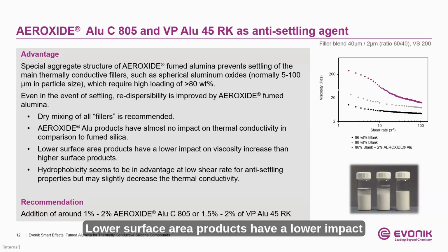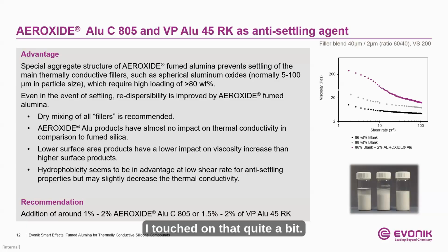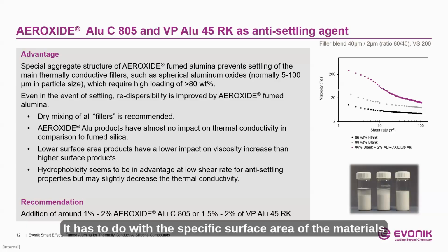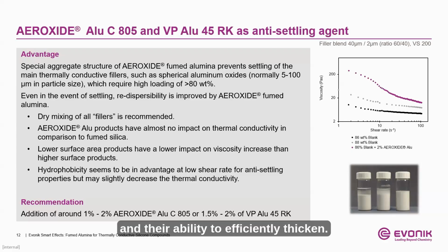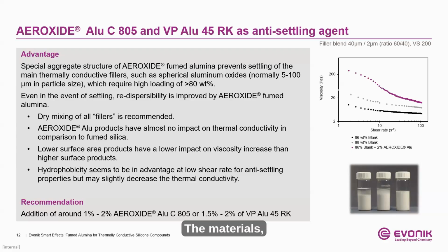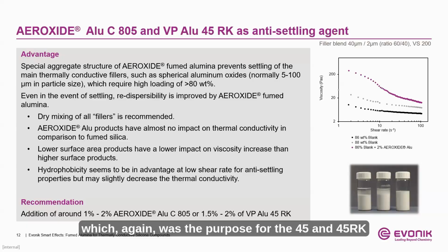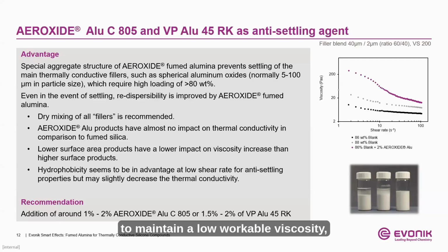The lower surface area products have a lower impact on viscosity increase than higher surface area products. I touched on that quite a bit. It has to do with the specific surface area of the materials and their ability to efficiently thicken the materials, which again was the purpose for the 45 and 45 RK to maintain a low workable viscosity, really was the inception or the reason for the inception of those products.